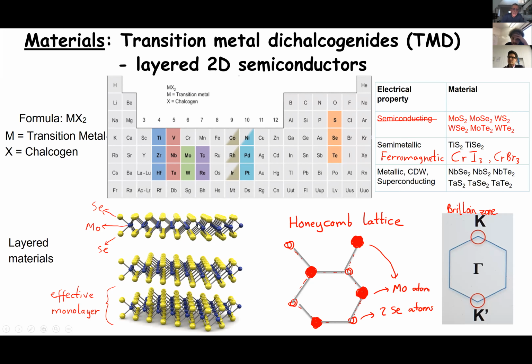So now if you take this monolayer, what I refer to as the effective monolayer, and if you look at it from a distance, we see that it looks like a honeycomb lattice where A and B sites are drastically different. So basically on one side, we'll have the transition metal atom, and the other side would be the two chalcogen atoms from the two layers above and below. Okay, so it's a massive graphene-like system. The inversion symmetry is broken, but the